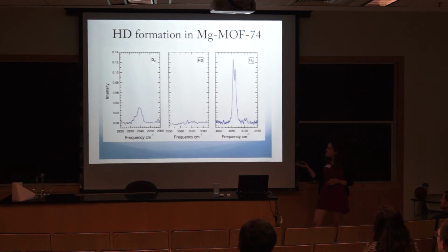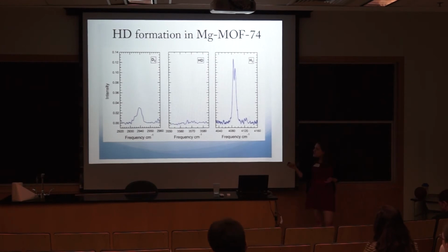So getting back to our results. We were studying mixtures of hydrogen and deuterium, mainly to do selectivity work. We weren't expecting to see this formation. We were doing this experiment, we got a nice peak in the deuterium region, a nice peak in the hydrogen region, we had a 50-50 mixture. And then we decided to be done for the day, valved the system shut, so we had the gas in, and just left it. So it warmed back up to room temperature from about 77 Kelvin. We came back the next day, we cooled down, and we got this. So that's a very clear peak in the HD region.